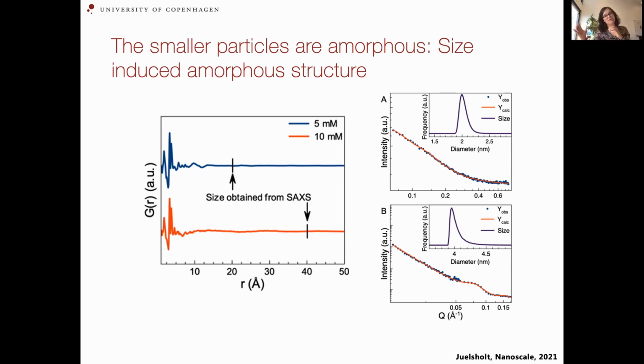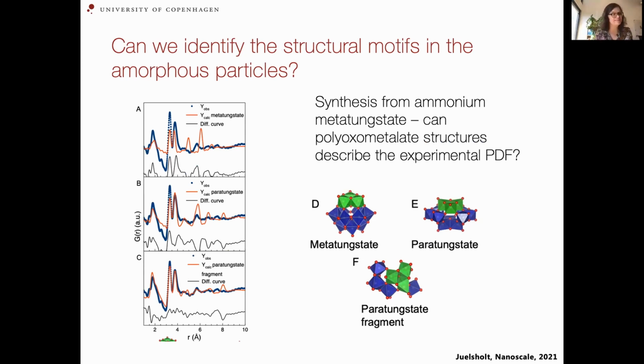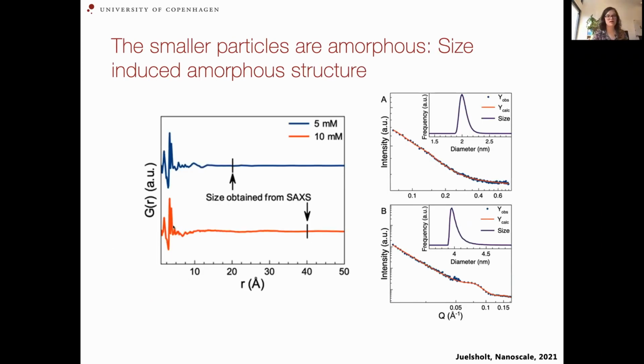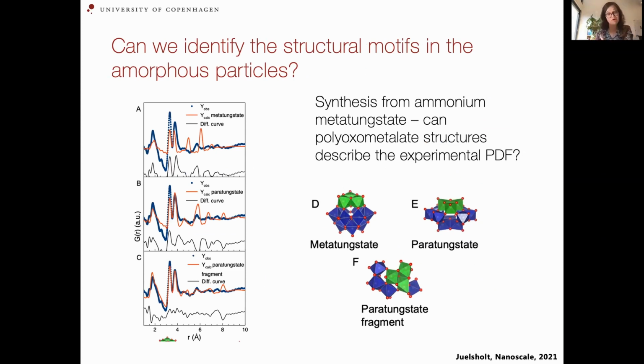But we could then use a different method, which is small angle scattering. The small angle scattering will instead give us not the atomic ordering, but the size of the individual particles. And this is SAXS data, and it's not so important, but what we could find is that if we analyze the SAXS to find a size, then this is the size here plotted on the PDF scale. So that again shows that we have amorphous particles because they're much larger than the extent of ordering in the materials. And we can also start analyzing these peaks here that we had at lower r to understand what is the atomic arrangement in the amorphous materials.